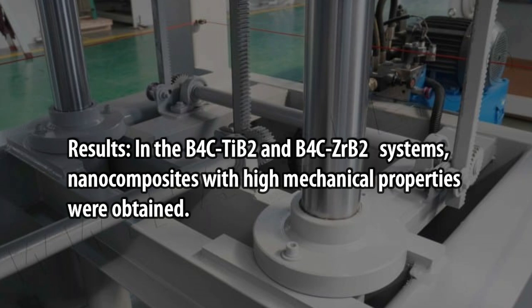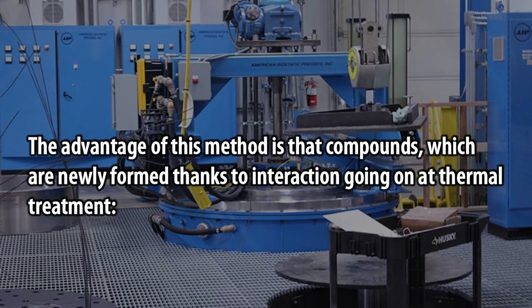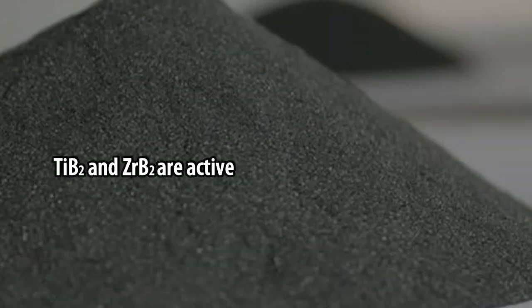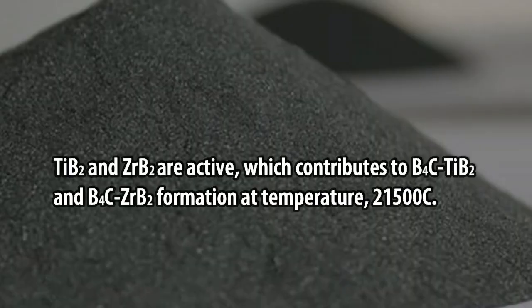properties were obtained. The advantage of this method is that compounds, which are newly formed thanks to interaction going on at thermal treatment, titanium diboride and zirconium diboride, are active, which contributes to boron carbide titanium diboride and boron carbide zirconium diboride formation at temperature 2150 C.